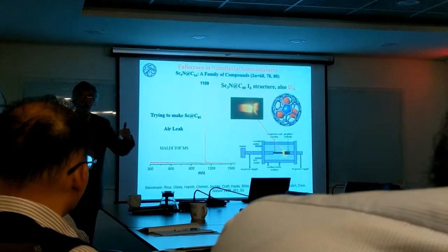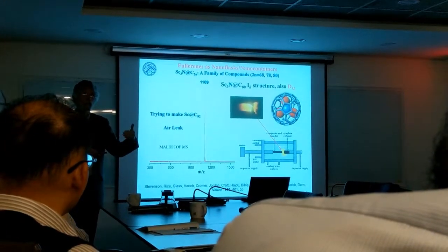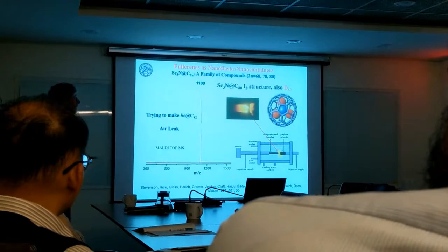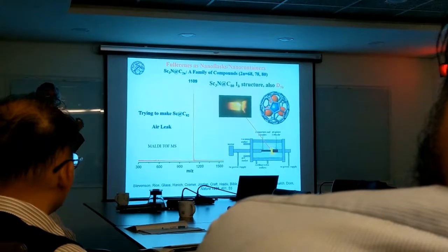And with air comes nitrogen. And with nitrogen, you have the possibility of forming other things. Okay? And what they discovered was that they were getting a scandium nitride, or 3 scandiums connected to a nitrogen cluster. So this is the first of the kind. This is called a cluster fullerene, because it doesn't have just 1 atom or 2 atoms inside, it has a cluster of atoms.